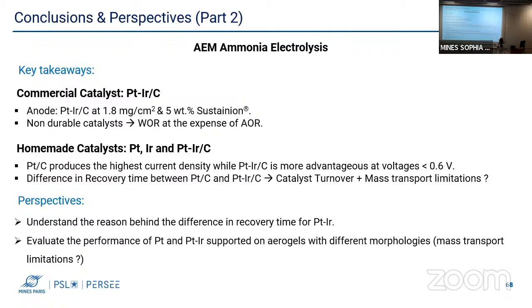And the slight difference in the recovery time between platinum and platinum iridium on carbon means that there could be a problem of catalyst turnover, but also mass transport limitations inside the pores of the catalyst. And it could be interesting to prepare a support that has an optimum pore size, specifically carbon aerogels, because it is possible to control their pore size distribution. It would also be interesting to understand the reason behind the difference in the recovery time in the future.